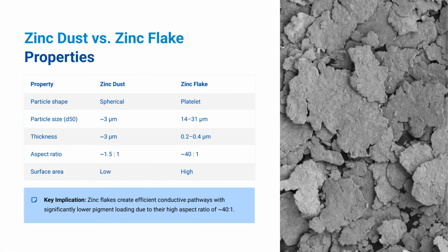This slide compares the physical characteristics of zinc dust and zinc flakes. While zinc dust particles are small and roughly spherical, zinc flakes have extremely high aspect ratios, approximately 40:1. Although the flakes are larger in diameter, they are extremely thin, typically only 0.2 to 0.4 microns. This platelet structure dramatically increases the available surface area and creates more efficient conductive pathways within the coating. The key implication is that zinc flakes can provide corrosion protection with substantially lower zinc consumption.